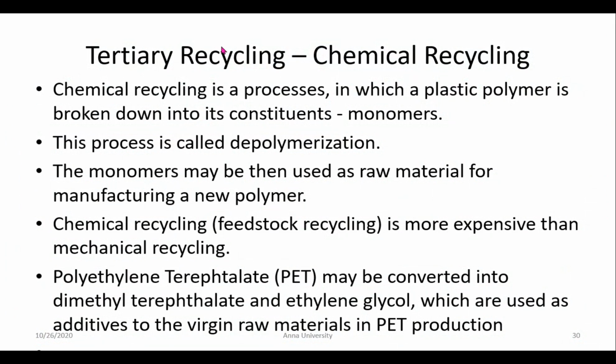This is more advantageous when compared to primary recycling, because if you take the case of mechanical recycling, we may not be able to produce a similar product when we reprocess the material. But when we take this tertiary recycling or chemical recycling, since we get back the monomer, it can be polymerized to give a polymer which can be used for producing the same products. But there are many disadvantages as far as chemical recycling is concerned, because it is more expensive and a lot of chemicals are introduced into the water body or land resource when you do this chemical recycling process.